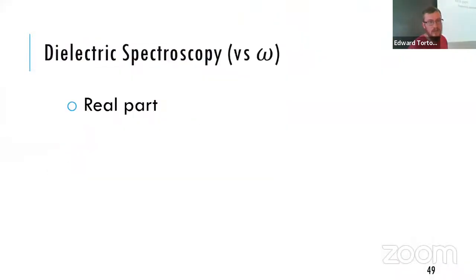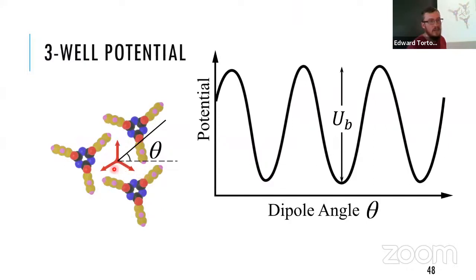And living in the TPP channels, you have these basically three directions the dipole wants to point because of the blades, but each layer gets rotated 180 degrees from the last, and so those three directions shift. So depending on the length of that double rotor molecule, you can force them to live in potentials that force them to align, versus a different length, which forces them to anti-align. And so we can actually see, I didn't include plots for it, very different behavior of the rotors, depending on whether they live in symmetric or anti-symmetric wells. So those ones are pretty cool.